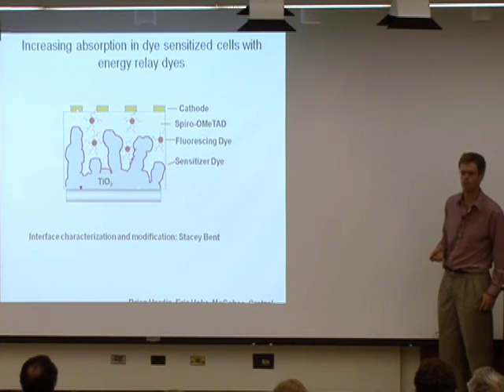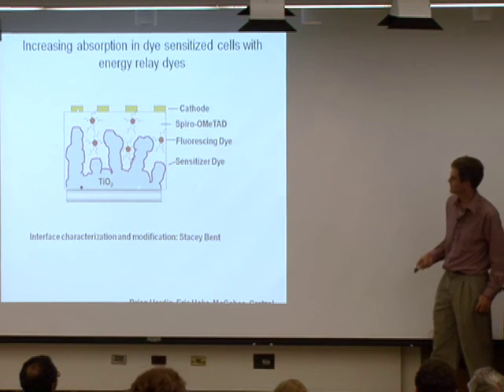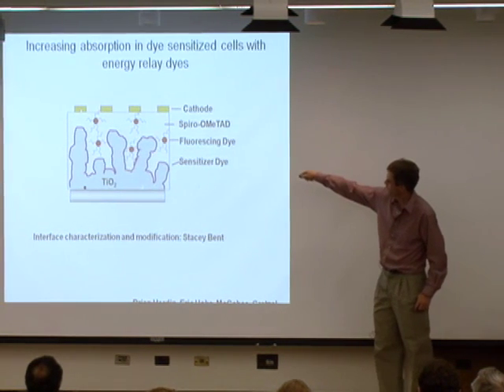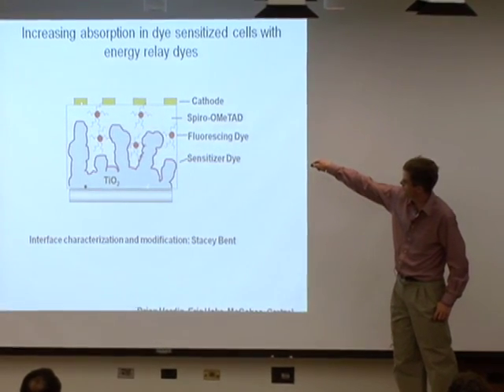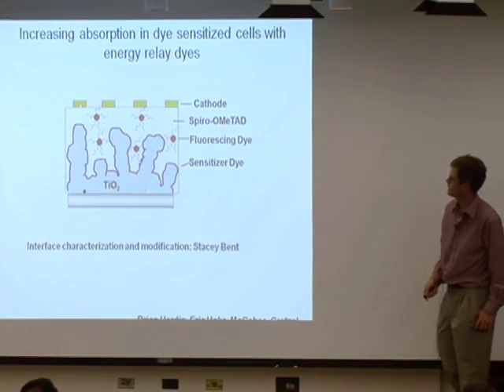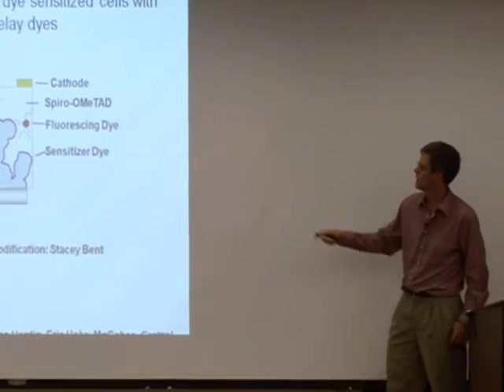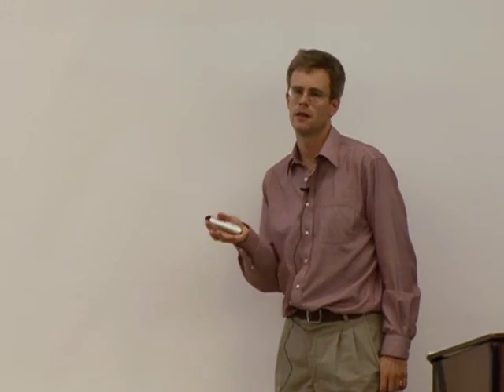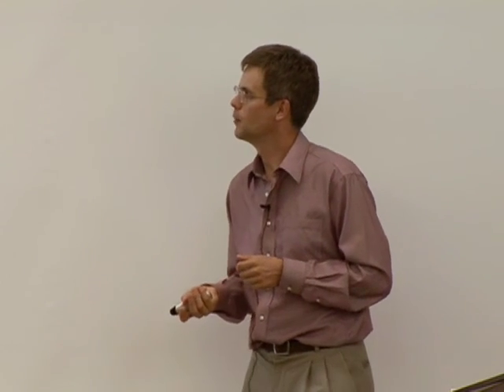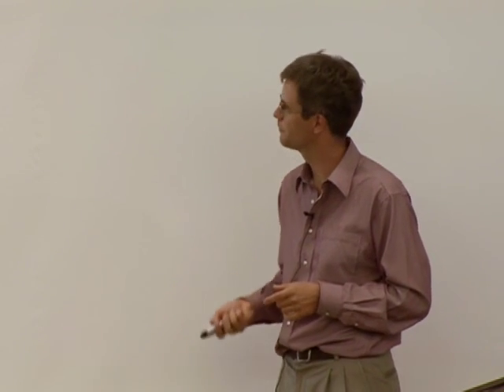Another approach we're using to improve these cells is Stacy Bent is going to put a very, very thin barrier on the titania, and it'll be so thin that it will not block the desired forward electron transfer, but it will slow down the back transfer. And it turns out that the forward transfer is faster than it needs to be, so you can slow it down a little bit without hurting the performance, but slowing down recombination will be very helpful and should boost the efficiency of these solar cells.